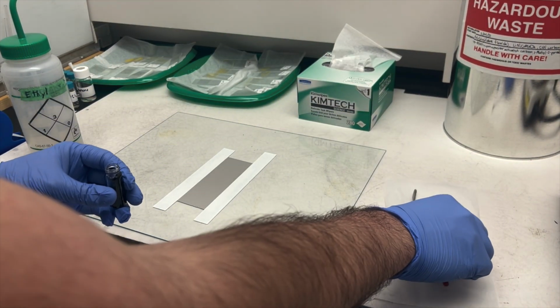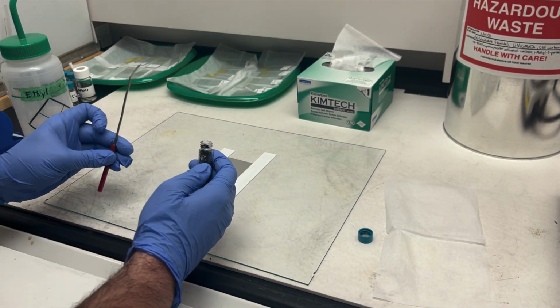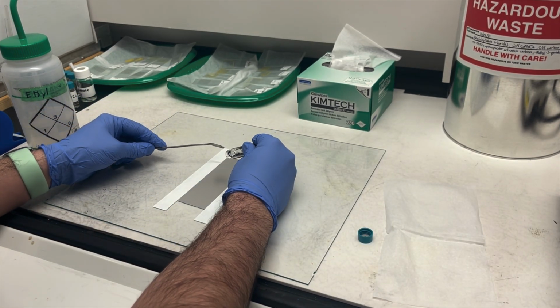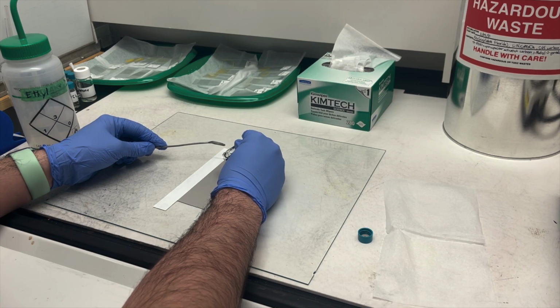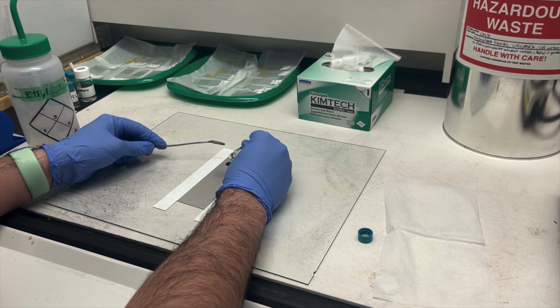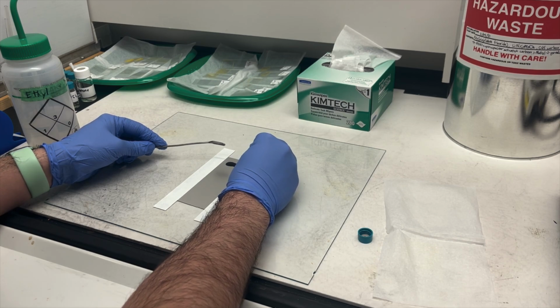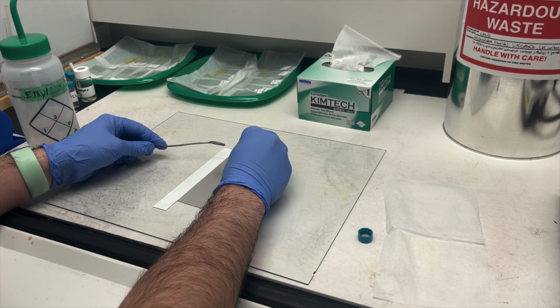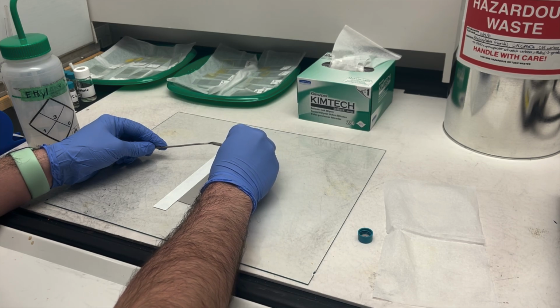With the foil smoothed out and secured, we are ready to deposit the slurry. We will take our clean scoop and start by trying to pour out as much slurry as we can. We want to do this in a bar along the top of the foil. It doesn't need to touch the tape, and is actually better if you keep the material further from the edges.